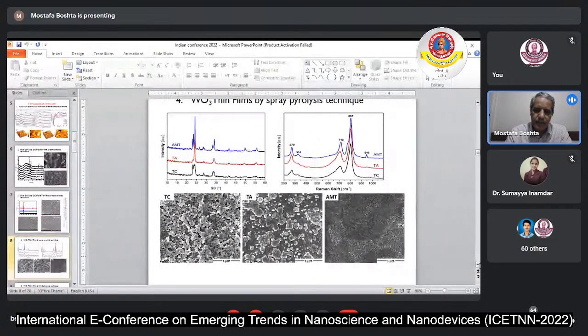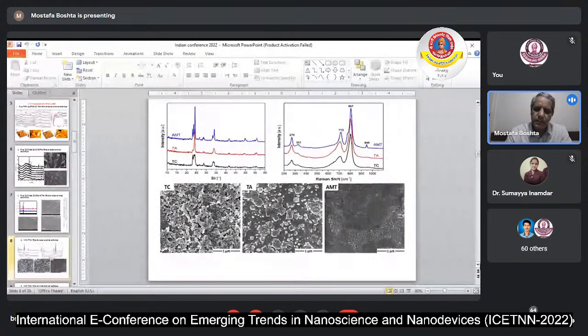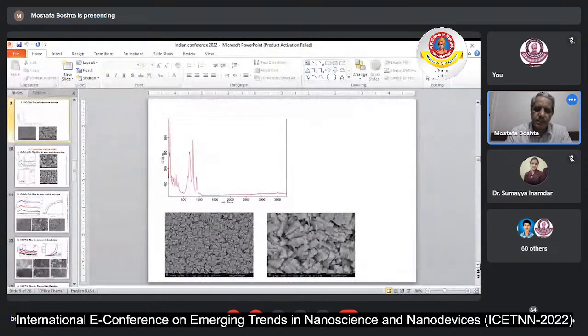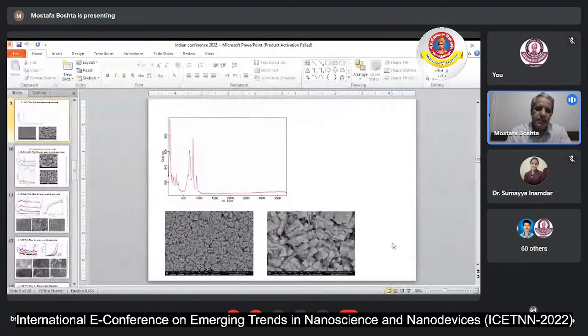After we finished tungsten oxide by spray pyrolysis, we now try to deposit tungsten oxide by the hydrothermal method. We are still working on this material, and we haven't completed its characterization. We only made a Raman measurement, and we confirmed that this is tungsten oxide. And we also have a scanning electron microscope image. As we can see, there is a different surface structure than with the spray pyrolysis technique. This different structure appears on the surface of the material. It will lead us to a new application and a new use for this different structure.